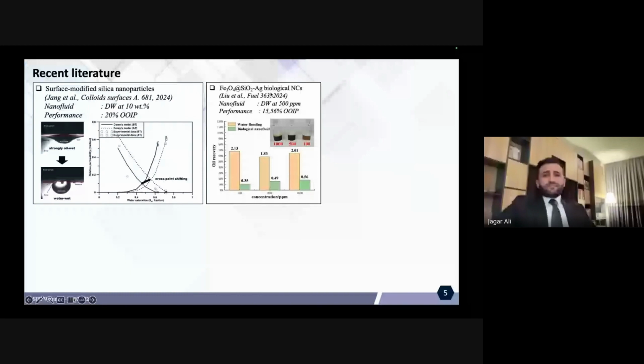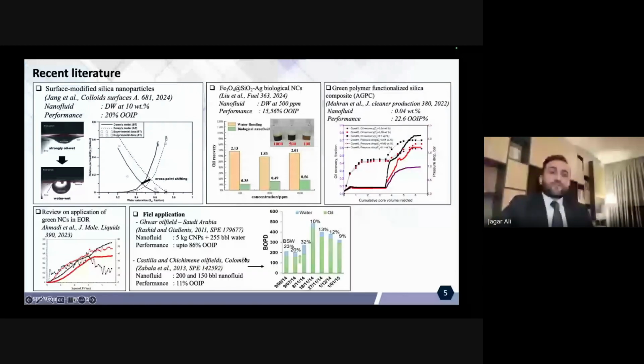Another research work was published by Liu et al. in Fuel in 2024 about Fe3O4 at SiO2-Ag. They prepared this nanomaterial from biological sources, from some bacteria, and it is reported as a green-based nanomaterial. And by injecting a nanofluid with only 500 ppm, parts per million, they increased oil recovery by 15.56%. This is a good achievement.